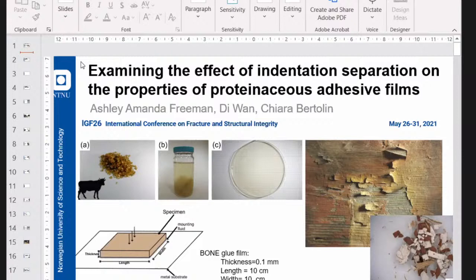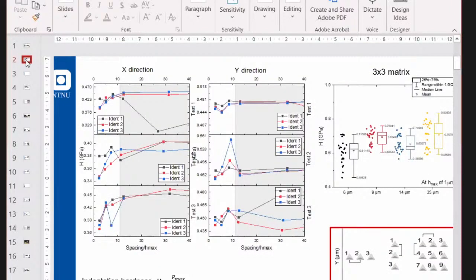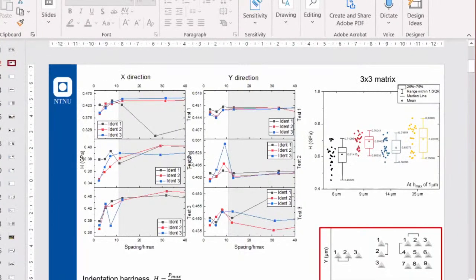To do that, we need to look at the separation between the indents, so the sequential indents that we did. And we did 3 different orientations. Let me go to the next one, which you can see in this red box. We did it in the X direction, so the spacing varied between the indents. If we had indents 1, 2, and 3 in the X direction, in the first schematic, this separation would be the same. It would be anywhere from 3 microns up to 100 microns.